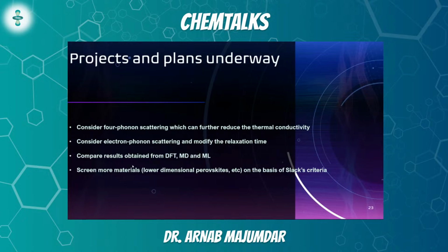Secondly, a very important factor is electron-phonon scattering. And we haven't considered that either. But if we do consider the electron-phonon scattering, the relaxation time might actually change quite a bit. This will significantly affect the results.